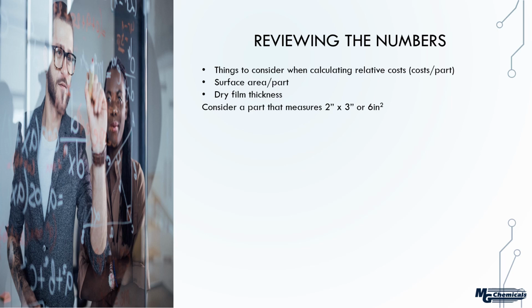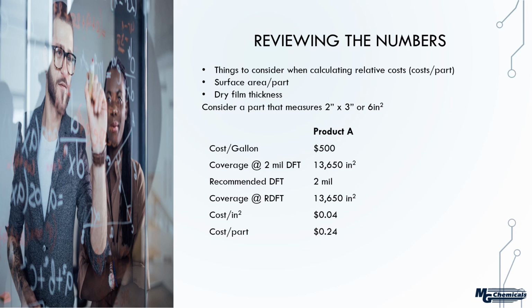So let's for example consider a part measuring 2 inches by 3 inches to give us 6 square inches. We take an off-the-shelf product A, at a cost of $500 per gallon. Now the coverage at a 2 mil dry film thickness is 13,650 square inches. Now we calculate these efficiencies, so that is something that we provide. That is found in our technical data sheets, and we try and standardize it over the same dry film thickness. So here we're going to use 2 mils. Now let's say 2 mils is also the recommended dry film thickness, meaning that in our opinion you get maximum performance with 2 mils of dry film thickness. So therefore the coverage at the recommended dry film thickness doesn't change. It's still 13,650. The cost per square inch is simply 500 divided by the coverage. Comes out to 4 cents per square inch. And then you multiply it with the surface area, you end up with 24 cents per part.